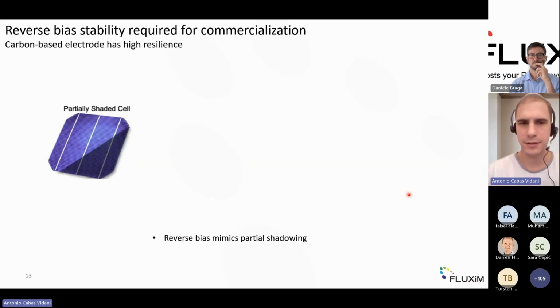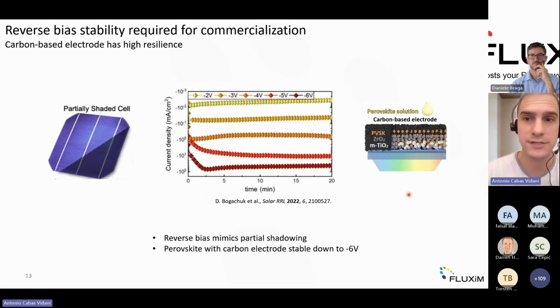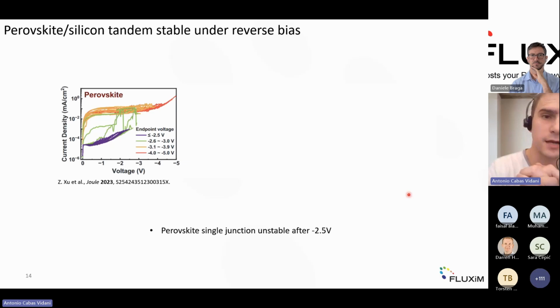And the perovskite is known to be rather unstable, or I believe to shunt and destroy itself if you keep it at reverse bias conditions for long. But what was observed was that if you have a carbon-based electrode perovskite, then it can withstand a negative voltage up to -6 volts for 20 minutes. So this is a very specific kind of perovskite that would indeed be suitable for outdoor conditions, real outdoor conditions.